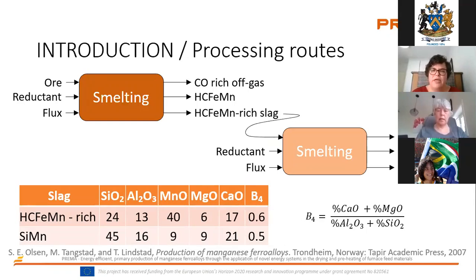So what they do is then feed that slag into their smelters to produce silicomanganese. In this instance, the slag produced in silicomanganese production is also discarded. Also, these furnaces tend to be closed, so they collect the CO-rich off-gas. And there's a lot of interesting things that people do, like heating water, and even in Norway they heat some of the sports fields so that they can play sports in winter, by combusting the CO-rich off-gas. So in all these instances, wet scrubbers are used.